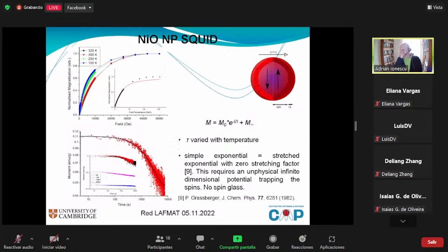And as I said, there was one postulation that this has something to do with a spin glass or a superparamagnetic behavior. We tried to model a superparamagnetic antiferromagnet by using the Néel formula, but it didn't work very well. And then we modeled a spin glass where you make a measurement, you saturate your sample, and then you measure the decay of the remanence in time and fit this to the equation shown here. But the results gave some unphysical results, so it didn't seem that it had really anything to do with spin glass. That said, I must mention that there was not much more research done into spin glass in the last decades, to my knowledge. So I don't know whether more information is in the meantime available.